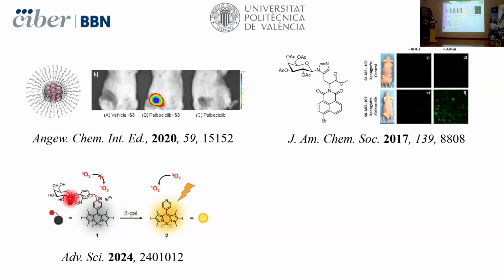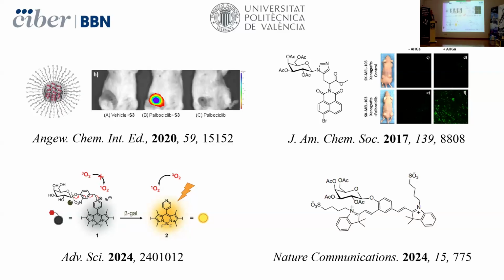Beta-galactosidase in senescent cells just hydrolyzes that bond, and that produces that molecule that is highly fluorescent, but it's also a photosensitizer. So if we irradiate the molecule with light, we can obtain singlet oxygen and kill senescent cells. So we have a system in which we can detect and at the same time kill senescent cells. This is a theranostics system, and this is another example in which we were able to detect the burden of senescent cells in animals, just making a simple measurement in the urine.